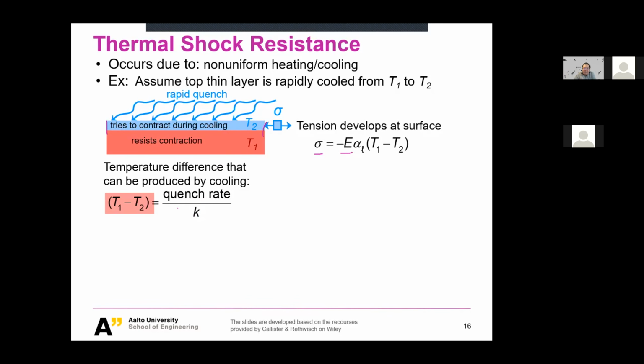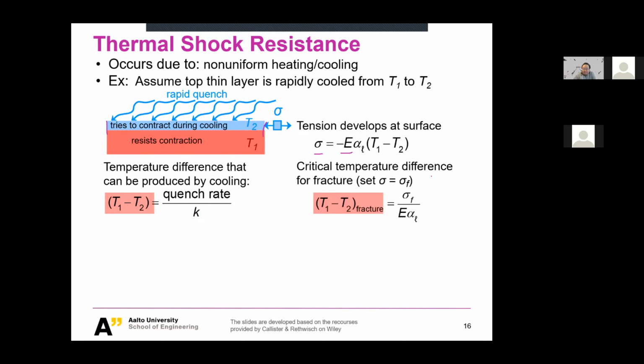So that means we would have a proportional relationship between the temperature change and the quenching rate. And as I just described, we would expect some fracture of the layer material, the surface material. So let's assume it's a rather simple case, but you could imagine when we have cleavage fracture, this completely makes sense, right? So we set a critical stress sigma F, which represents the failure stress, meaning when the material reaches the sigma F, we will get fracture.